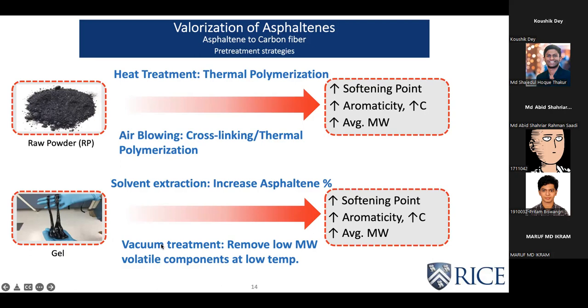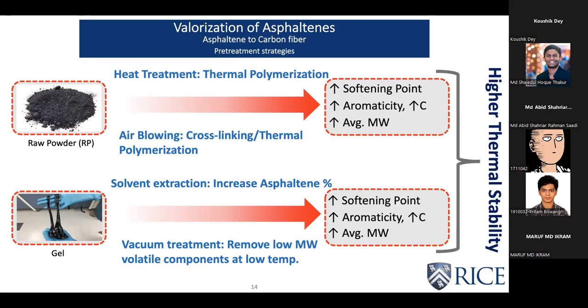All of these strategies were meant to achieve higher thermal stability, because that is a very critical criterion needed for carbon fiber production. And from different tests, finally we chose two samples. One was the raw powder as it is, and the other one was the solvent-extracted gel for making carbon fiber.